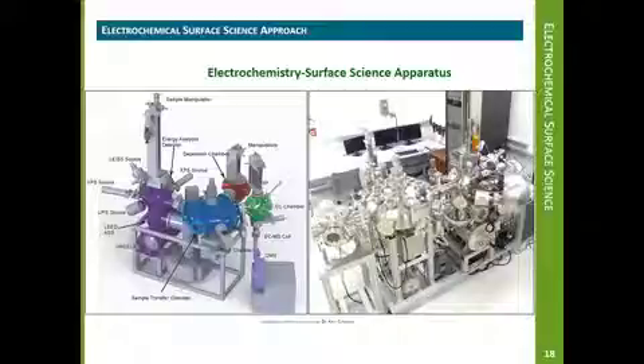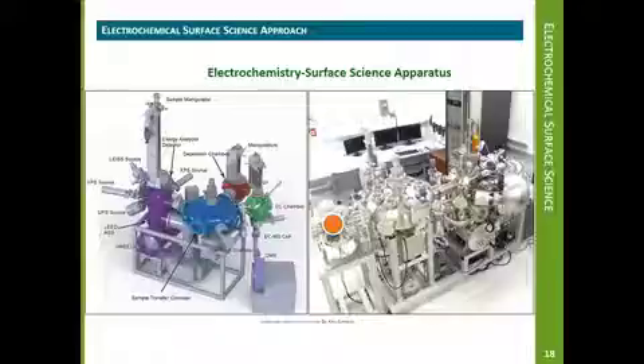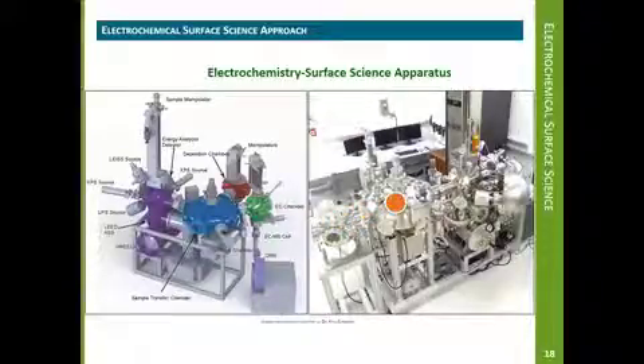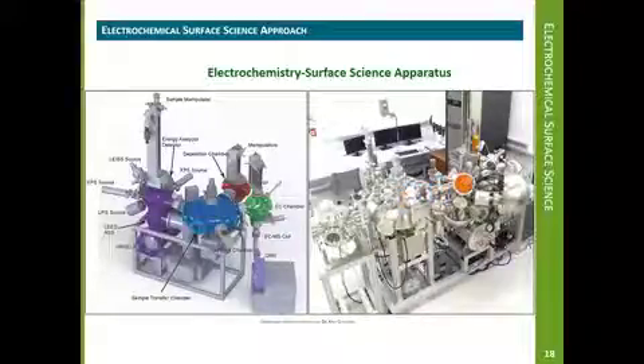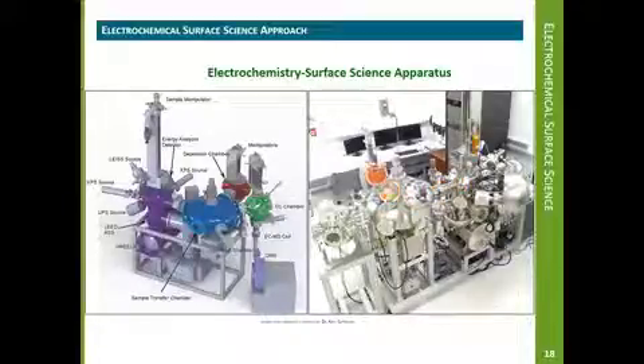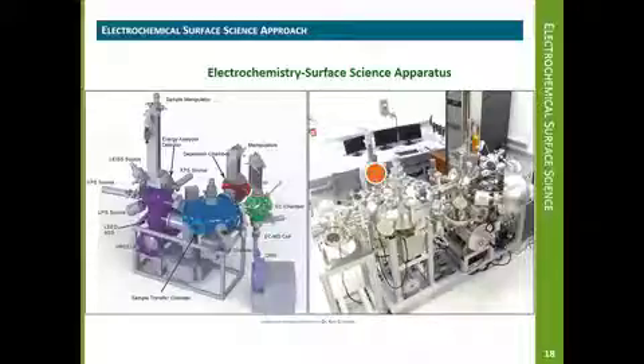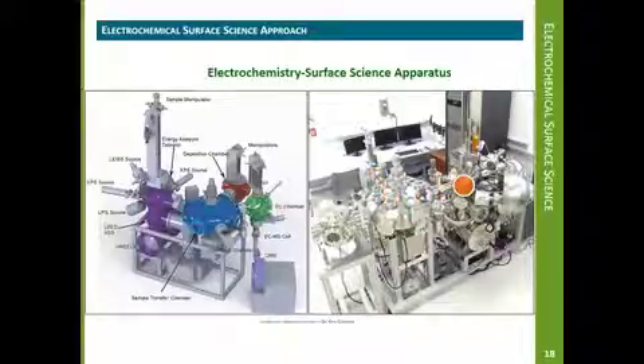A typical experiment may start with the catalyst preparation via the deposition chamber, followed by transfer into the transfer chamber. The catalyst is then transferred to the surface analysis chamber for initial state characterization of the surface prior to electrocatalysis. The sample is later moved to the electrochemistry chamber for catalysis-related electrochemical experiments. At selected stages of the reaction, the electrode is removed from solution under potential control in a process called immersion. The electrode is returned to the analysis chamber to scrutinize for any reaction-induced changes in the surface structure and composition. This analysis-catalysis-analysis iteration is repeated quite a few times to establish important relationships between the various interfacial parameters. Nowhere in the experimental protocol is the sample exposed to uncontrolled environments such as air.